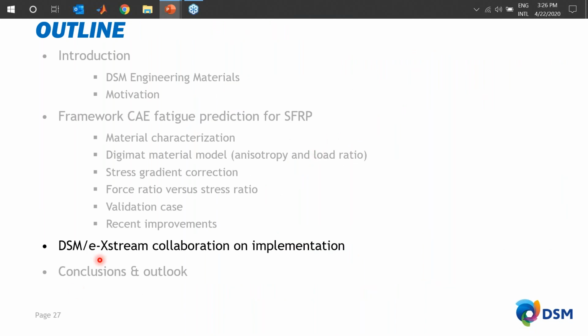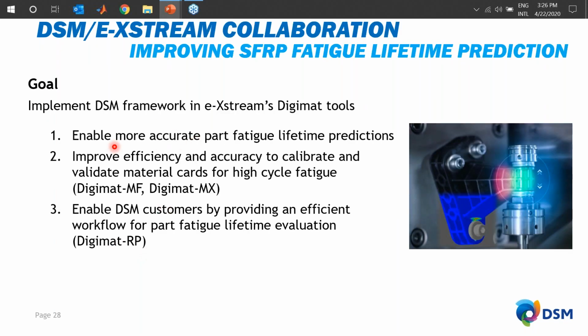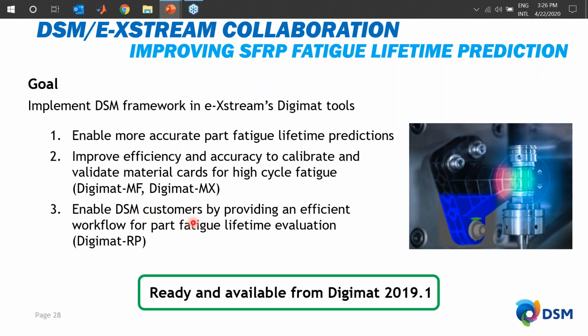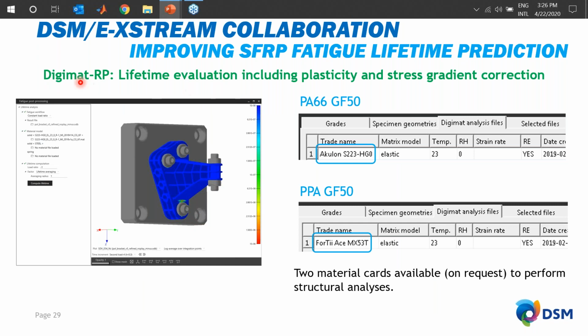The reason why it might be of interest to you that we had a collaboration is that E-XSTREAM, the company behind DIGIMAT, also implemented this workflow. We had a goal to implement this to enable you to do more accurate fatigue lifetime prediction at part level, to simply enable our customers using our material cards. And it's ready and available from DIGIMAT 2019.1, even including the plasticity correction. That means that you have an RP, a post-processing tool to compute your local lifetimes. And we also supply 2 different material cards, polyamide 66 and PPA, both with 50% glass fiber, that are now available, albeit on request, to perform structural analyses.